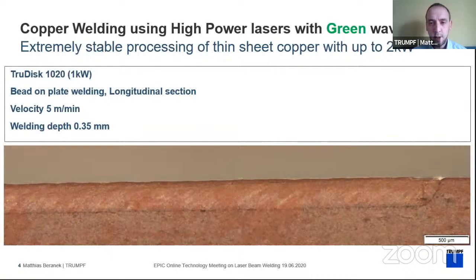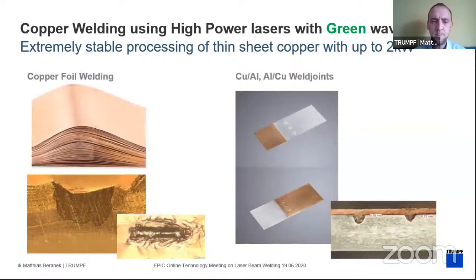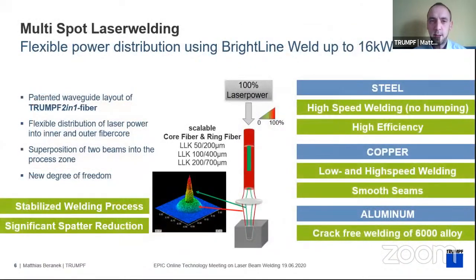We talk about comparably shallow welding depths, like in this case 0.35 millimeters in bead on plate copper, but with a very extreme stability of the welding depth. And this cannot be achieved with infrared, but only with the green one. And this is something very new. Also, we see the classical battery cell applications like foil stacks will become feasible with those green lasers, as well as the mixed metals, so aluminum with copper in that case, where we just want to have such extremely stable welding depths in order to maintain that.